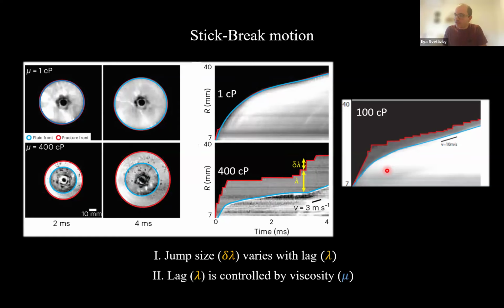So injected volume in time. I'm not sure that I'm following. There is no additional injected volume during the time the crack runs. So you always start with the same crack. You fill up the crack with fluid, and it nucleates. And during the time the crack runs, there is no additional injected